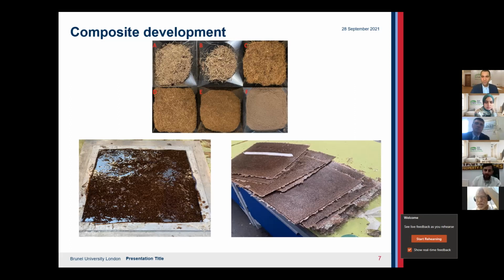So I have done the hand layup technique, which is shown in the lower left image. And then after the hot press, it shows how the panels were developed, which were roughly around 30 centimeters by 30 centimeters, which were then cut through a bandsaw into the standard of 10 centimeters in length and 1 centimeter in width, and tested through the various testing procedures that have been explained.